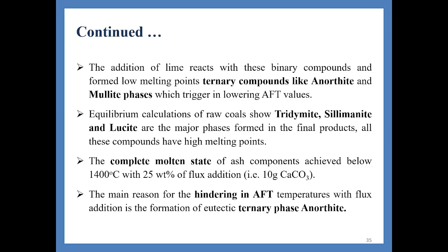That is very important. The main reason for the lowering of AFT with flux addition is the formation of the eutectic ternary phase anorthite.